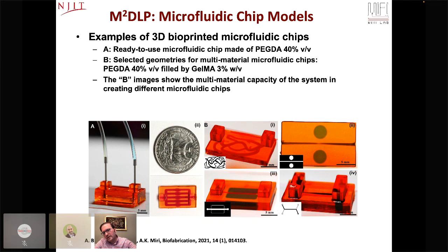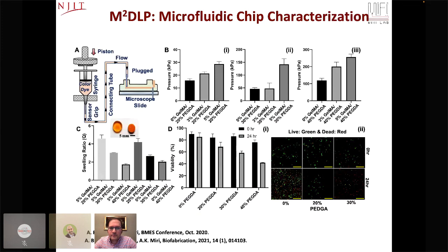So now you do the characterization in terms of printability. You look at the structural property, how the structural property works. One of the key questions: how stable is the microfluidic hydrogel chip? And one of the easiest ways is to do burst pressure. So we made a customized experimental apparatus to do the burst pressure. And we showed that the burst pressure is pretty high and very comparable to even PDMS systems. And our platform was very stable up to 1 week because PEGDA is not degradable and gelatin can be tuned in a way up to 1 week. You have very minimal variations in the property.